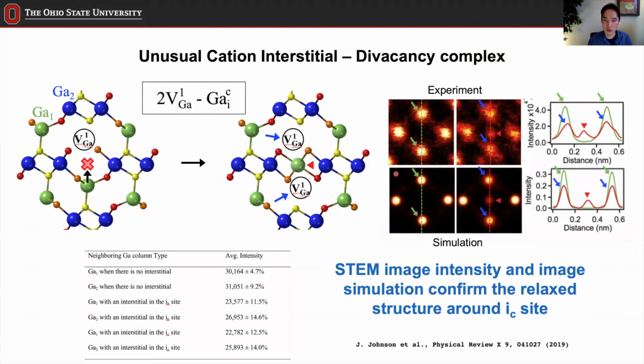Okay, so we also ran image simulation from the model. We constructed the model that we think is happening. This is the area where there's no defect, and this is the area where we introduce the defect, and the same thing is happening, right? When you have the interstitial column, you have the extra intensity, but when the same number of vacancies are introduced, you get the lowered intensity. So computationally, it was also possible to recreate what we saw in the experiment. Yeah, so that's how we confirmed the interstitial-divacancy complex. But this one was nearby the IC site, the red X here.